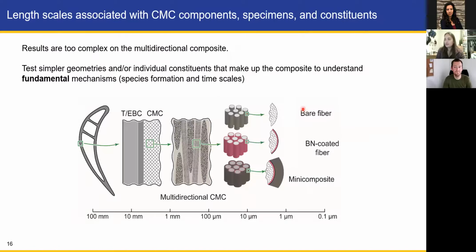So what I do is I break down that multi-directional composite and I study very simplified geometries. So this is a mini composite that has just about 500 fibers in one direction. So I study the microstructural evolution of those when they're exposed to water vapor. And then I also study just the coatings on the fibers themselves and just the fibers. So I'm trying to break it down and understand the more fundamental mechanisms behind the formation of those new species and the timescales over which they form.